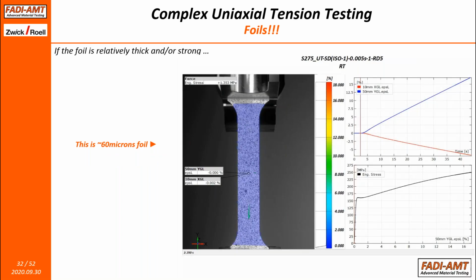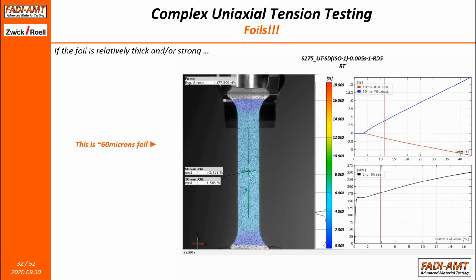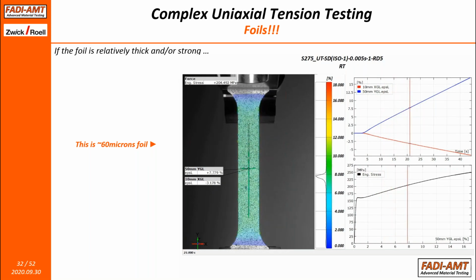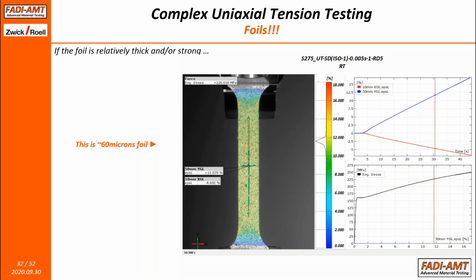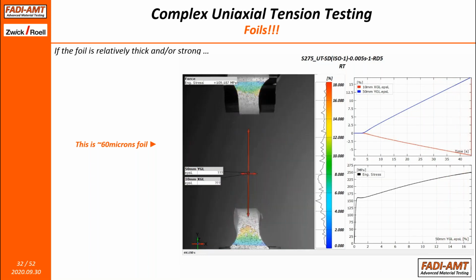The same thing applies if your foil is generous in terms of thickness. We always say internally that if it's above 50 microns, it's tolerable. You can put a couple of marks, like laser extensometer markers, or you can paint it for DIC. But in both cases, you must be very careful because you could potentially affect the sample you're trying to test, and if things are not done properly, it will lead to premature failure in the sample.